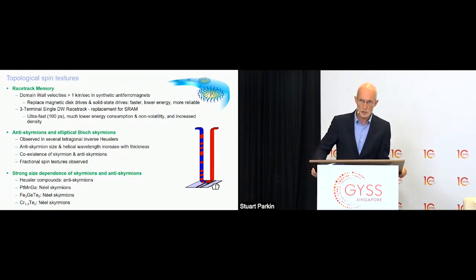domain wall, we could replace the fastest memory today, static random access memory, because this single domain wall racetrack can be ultra fast, 100 picoseconds. We've already demonstrated in the laboratory below 400 picoseconds, it would use much lower energy, would be non-volatile, and would have substantially increased density compared to today's static random access memory.